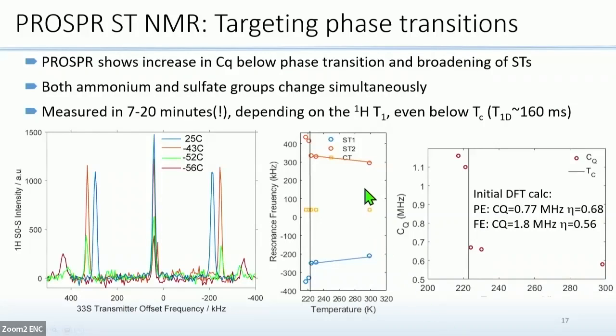And I'd like to emphasize here that all these spectra are measured in 7 to 20 minutes only, and they span over 800 kilohertz, depending on the proton T1. If you recall, I said earlier that we need very long T1Ds, and we saw here that even below the critical temperature, when the T1Ds were only 160 milliseconds, we still were able to measure very good signals. So that's very promising for us in terms of the broad applicability of this method.